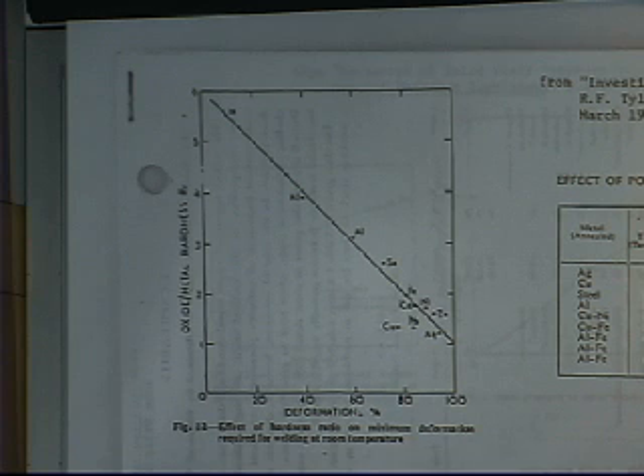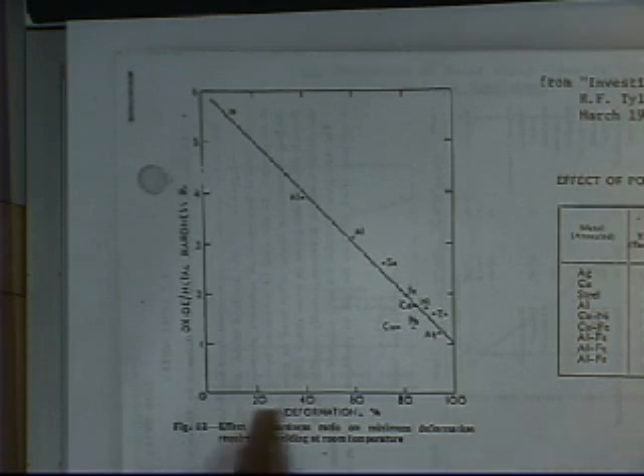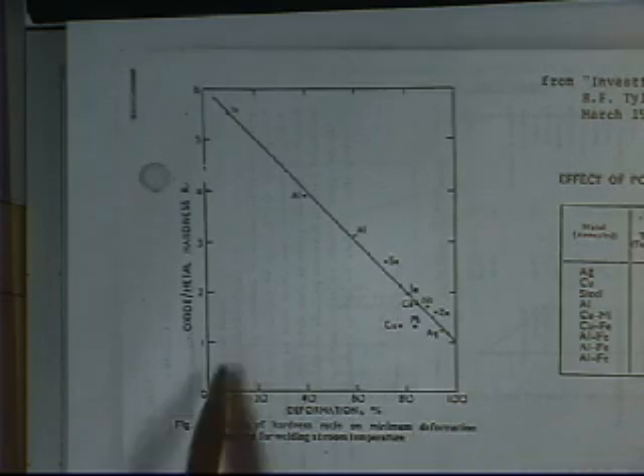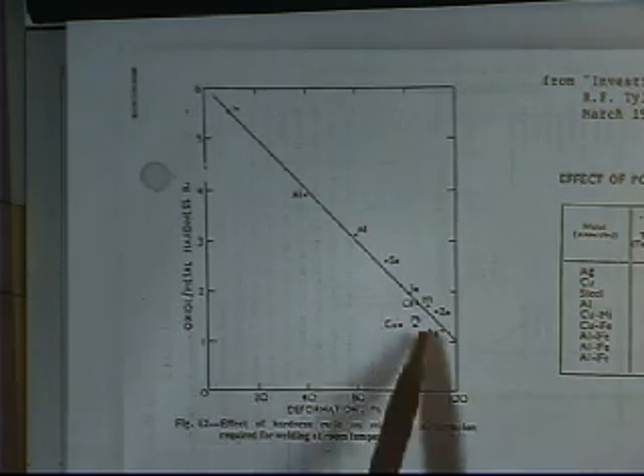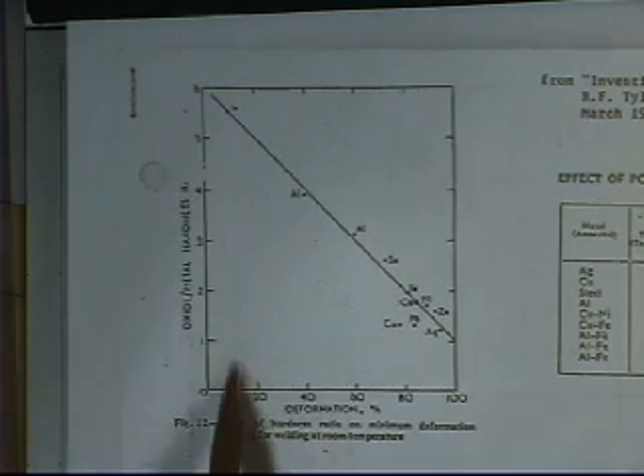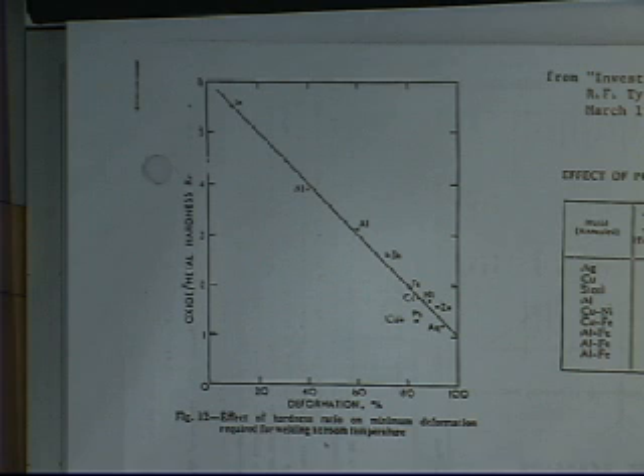If you look at the amount of deformation it takes with different metals in order to form a strong bond and plot it versus the oxide to metal hardness ratio, you find that various elements lie along here. And indium turns out to be the easiest material to cold bond. Indium is a very soft metal with a very high hardness oxide.